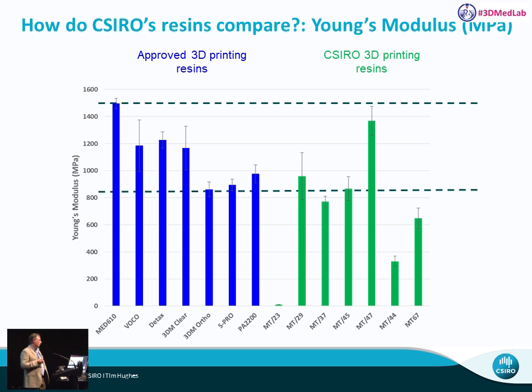So how do they compare to what's commercially available currently? These are some current 3D printing resins that are approved for medical use. And you can see this is measuring the Young's modulus by tensile testing compared to the CSIRO resins in green here. And you can see that they both cover a similar modulus range. There's nothing particularly special there.